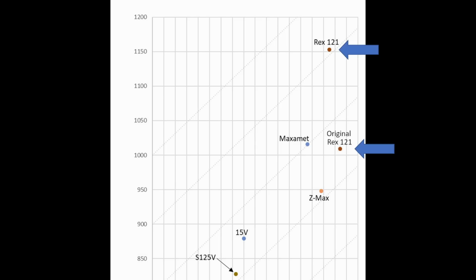And a lot of people will blame difficulty in sharpening on the steel being highly wear resistant. Like, oh, Rex 121, that's as wear resistant as steel gets. But removing material, grinding away material was not the difficult part. It was just like the burr would not come off and leave a clean edge. And in our defense, it was not difficult to grind because we were using CBN.